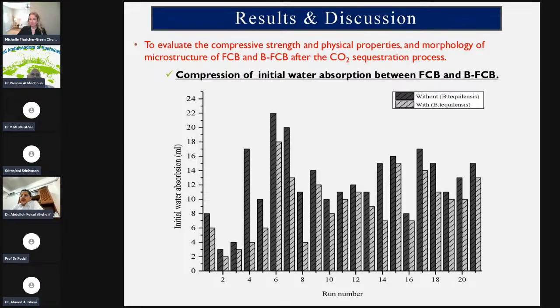If you look at the results, for the concrete with Bacillus bacteria, or biofoam concrete, there is the initial water absorption. For the surface of the break, it also produced self-healing already. The self-healing already occurred. That means the results show that the water penetration is reduced for the specimen using bacteria inside the concrete.